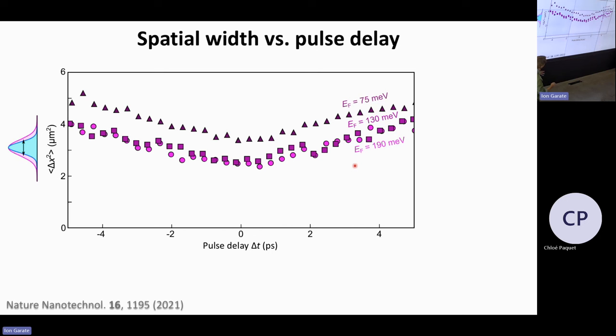So in reality, it's a little bit more complicated, but the best way to see it is that this width that we're getting is identical to the width you would get if you had a single pulse and looked at the broadening of that single pulse. It's completely equivalent to what we're doing with these two pulses and changing the relative spatial and temporal offset. And then what you're seeing is that, as a function of time, the width is getting larger. This is time zero, because of course it doesn't matter which pulse comes first, it's symmetric. So the more delay between the two pulses, the larger the broadening. And then the slope is your diffusivity.